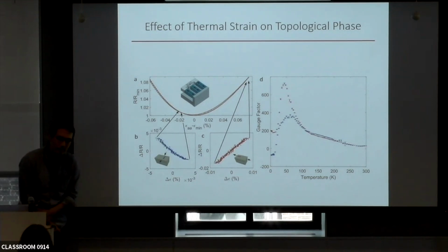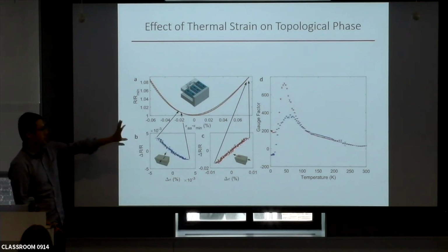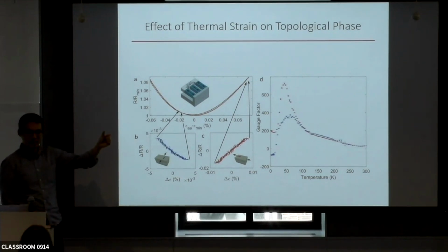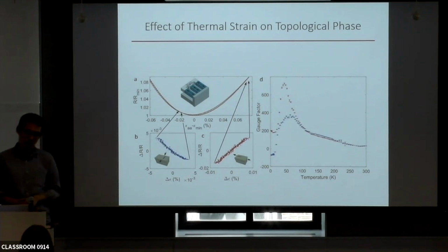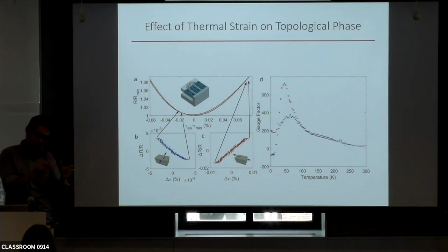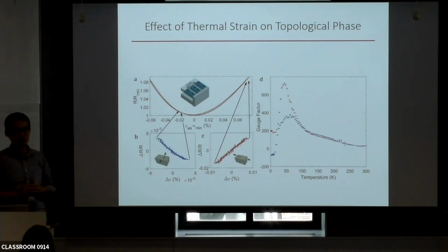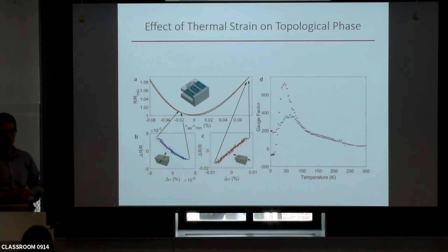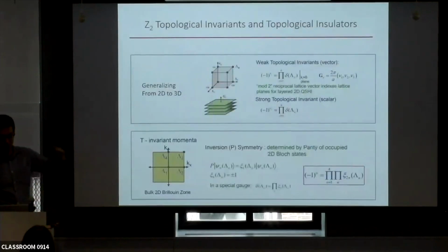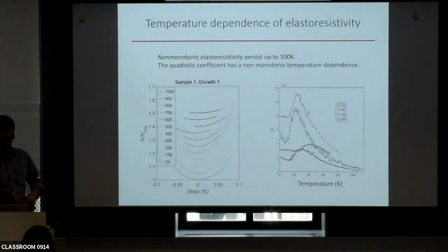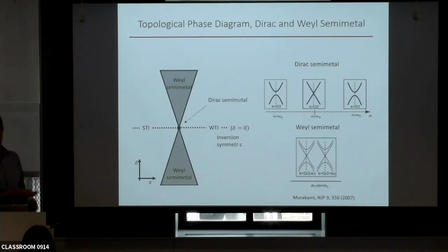Can you ever get into the Weyl phase? Not for all these bulk crystal measurements, because you need to break inversion symmetry. We're trying some thin plates, which potentially apply a vertical electric field. Okay, so you couldn't do inversion-breaking strain, that would just ruin it? Strain generally doesn't break it. You need something else. Usually inversion symmetry is already broken, and by applying strain you can probably induce a polar vector from that. We're thinking about looking for some inversion-symmetry-breaking material and seeing if we can use strain to go across this topological phase boundary. Like not around here, but maybe around here. That would be interesting too.